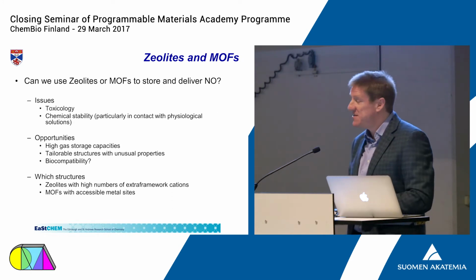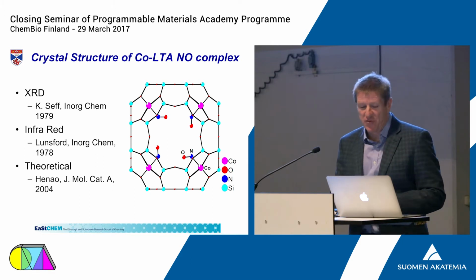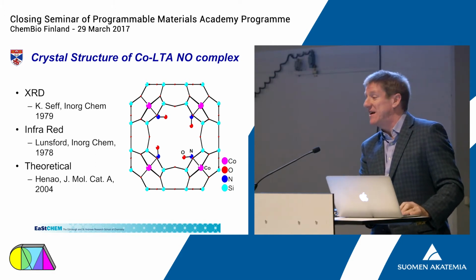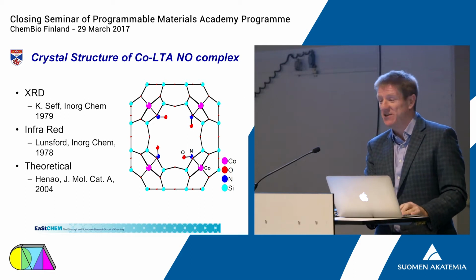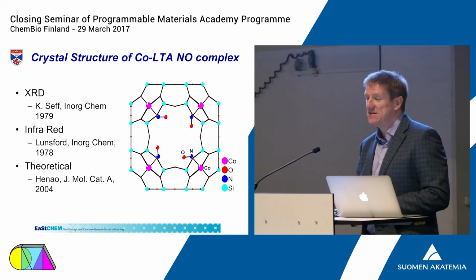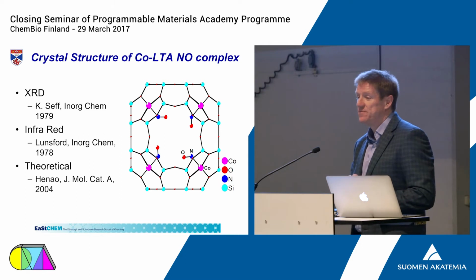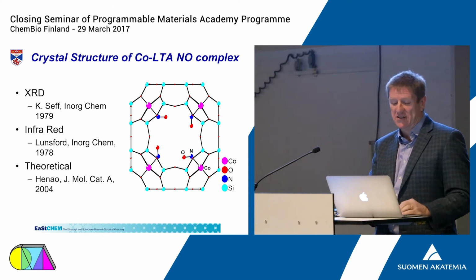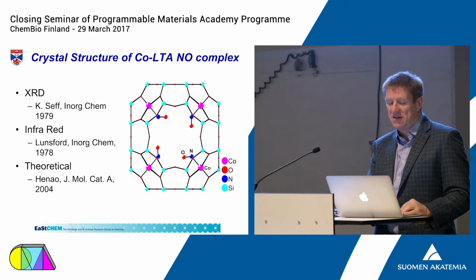So let's have a look. This is a picture taken from lots of work done in the car catalyst area. There was lots of work done in the 70s on how nitric oxide interacts with zeolite. So this is a zeolite structure, basically, the pores in the middle, and nitric oxide tends to attach itself pretty strongly to the metals in these materials. A zeolite is an aluminosilicate, right? And here we've got aluminium or silicon in blue, and then oxygen shown just at the corner of these things. And then other metals are around.